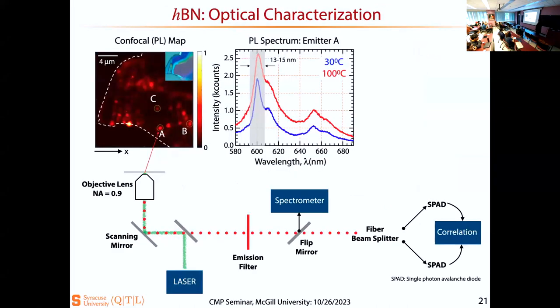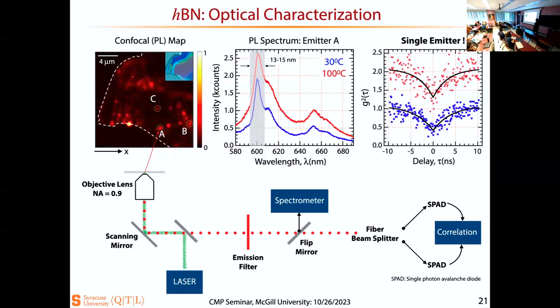Okay, then I'll quickly go through it again. Here is one of the flakes. Whenever we prepare our sample, the first thing we do is Raman spectroscopy, to determine that this is actually boron nitride and not just a residue from the substrate. Then we also do a photoluminescence map, in which we look at the integrated PL at each and every pixel, where the pixel size is half a micron by half a micron. This is how a typical photoluminescence map looks. There are many different local hotspots. When I saw this one, I thought maybe this is really there. But it's not. It's basically because of local inhomogeneity in either the sample or the environment.